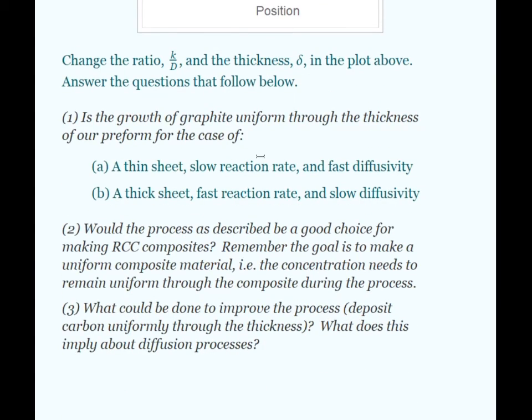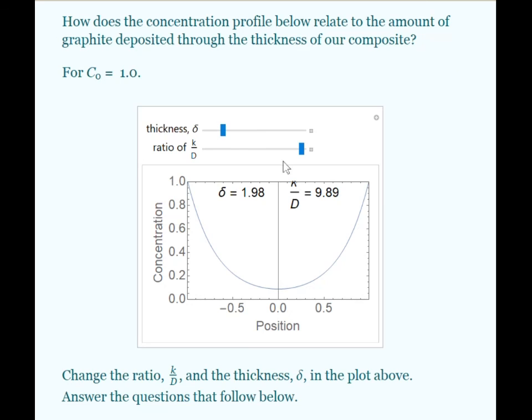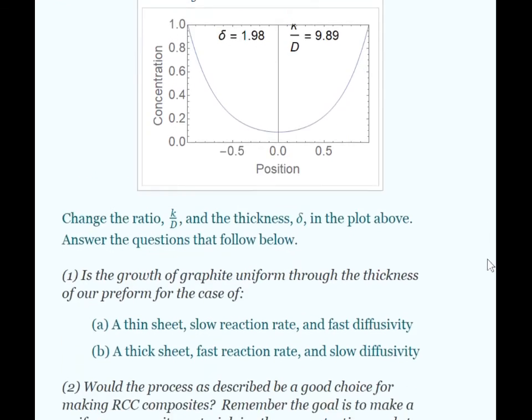So what is really done in practice, because this deposition process is used, is rather than count on diffusion, you blow the acetylene through the porous sample and then deposit it that way. And so that gets around the slow process of diffusion. You just blow the acetylene through.